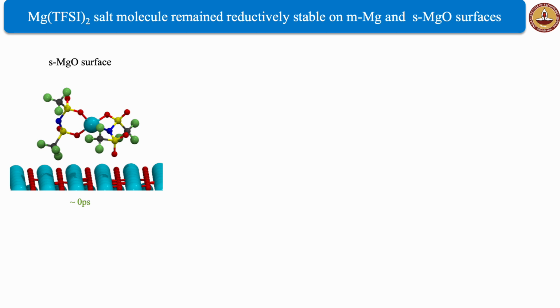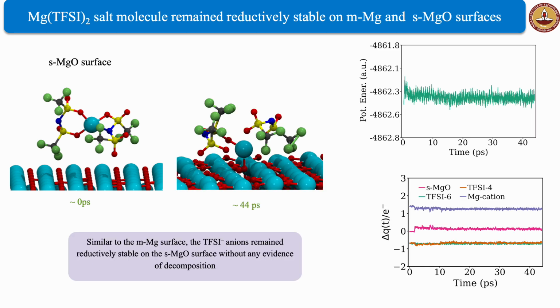Next, we check the stability of Mg-TFSI salt on the stoichiometric MgO, s-MgO surface, which is found to grow epitaxially on the Mg(0001) facet. Although the presence of magnesium oxide is expected to strongly influence the interfacial chemistry, similar to the metallic Mg surface, here also we didn't observe any decomposition of the TFSI anions, with minimal changes in potential energy and charge transfer. These findings suggest that both the metallic Mg and the stoichiometric MgO are inadequate models for capturing the interfacial processes in magnesium metal batteries, and highlight the need for more realistic models that account for passivation layers, defects, and other sources of surface heterogeneity.